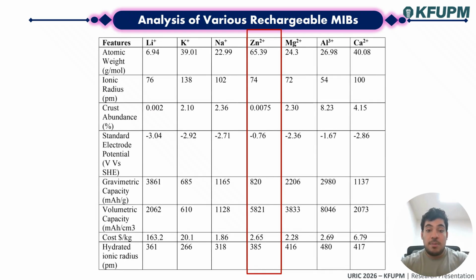Why are we using zinc ion? Zinc ion has many considerably good properties comparable to lithium. For example, the price of zinc is $2.65 per kilogram compared to lithium's $163. However, it has a comparable radius to lithium at 385 picometers, a hydrated ionic radius. Now my colleagues will discuss further on the scientific gap and the core idea of our work.